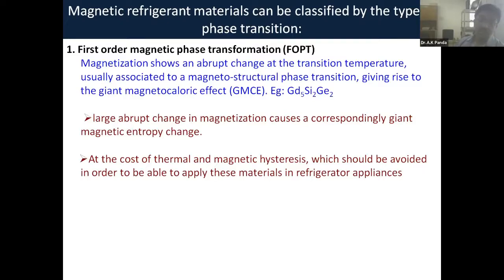What I mean to say is that along with the ferro-para or antiferro-para transition, or whatever it is, there is another crystallographic change within that temperature phase boundary. When these two happen together, what you find is a giant magnetocaloric effect. It is quite natural: when they both join together, you have a greater change in the magnetic entropy. But of course, there is a cost to it. What is the cost? It has some magnetic hysteresis.